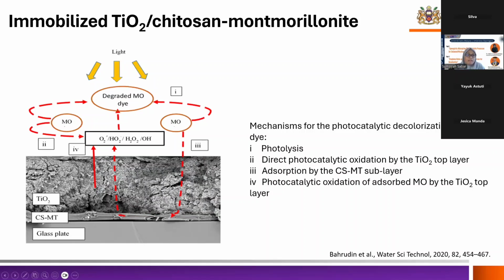Okay, so the adsorbent is only a very thin layer inside the titanium dioxide. And then the third mechanism is the adsorption by the chitosan sublayer, and then the photocatalytic oxidation of the adsorbed methyl orange by the TiO2 top layer.